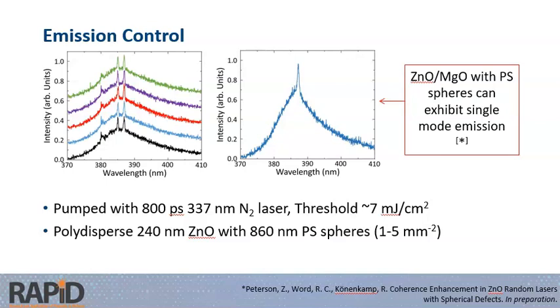Now one thing that some folks have done, and this gets to the core of the presentation, is to use very high quality structures embedded in the system of random particles to provide some control over the emission. Here in the top left graph you're seeing a set of five emission spectra, and you can see very clearly some laser peaks that stand out above the photoluminescence background. We have here two very clear peaks about 385 and 387 nanometers, and then a third peak about 380 nanometers. We've even been able to see one single peak. When we combine zinc oxide, magnesium oxide, and these very high quality 860 nanometer polystyrene spheres at low density, we're able to actually exert some level of control over the emission in this random structure. This is where you have a semi-ordered structure.